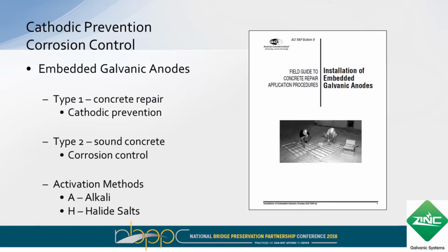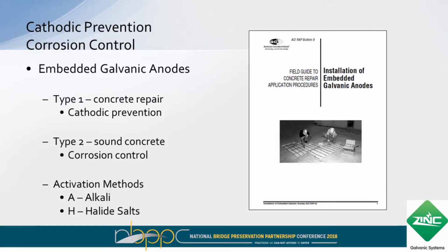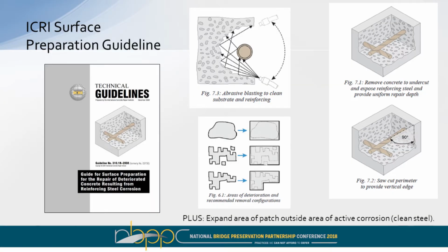But within that guideline, it defines embedded galvanic anodes as type 1 anodes, which are used for concrete repair and generally are considered cathodic prevention anodes. You have type 2 anodes, which are installed into sound concrete as more of a proactive preventative for corrosion control. And there are also different types of activation methods for galvanic anodes, either alkali activated or sometimes using halide salts. So, our first line of defense is to do the concrete repairs.